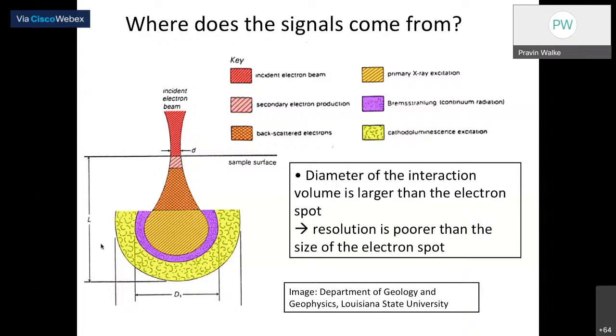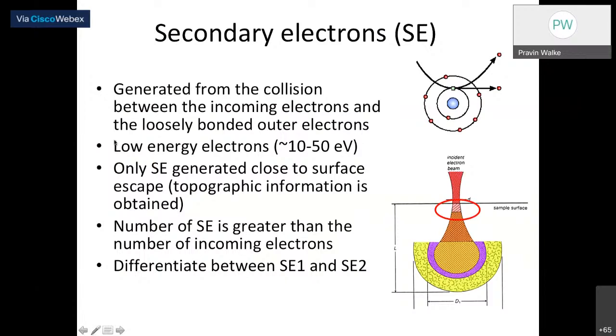So let's have a look at what the secondary electrons are. How are secondary electrons generated? First of all, your electron beam. In your specimen, you have various atoms, right? Atoms have electrons circulating around them in the external orbital. So what happens if there is a collision between the incoming electrons and the loosely bound external electrons, or outermost electrons, of that particular atom, right? After the collision, the electron loses some energy, and very low energy electrons get emitted, right? Those low energy electrons have an energy range between 10 to 50 electron volts. So they are known as secondary electrons.